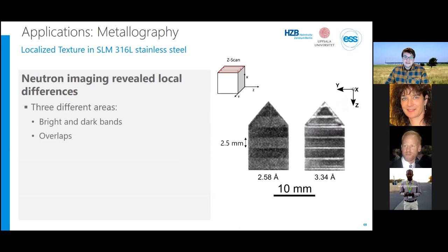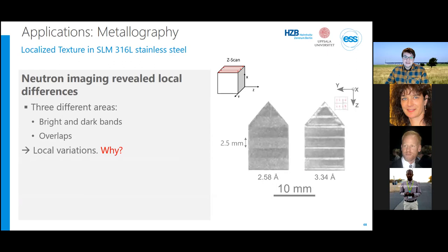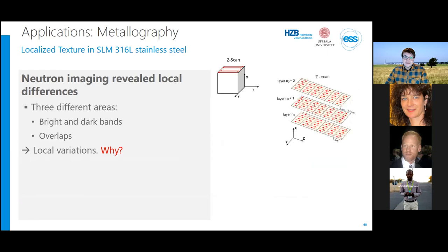Moreover, in this data set, we also observed local differences within the samples. In particular, for the sample with a Z-scan strategy, there are three different areas: bright and dark bands and overlap regions. So why do we see these variations with a 2.5 millimeter spacing? The answer is that the laser moved in the Z direction for only 5 millimeters at a time, completed the width of the sample, and then printed another 5 millimeters. Every second layer, however, was printed with a 2.5 millimeter shift.